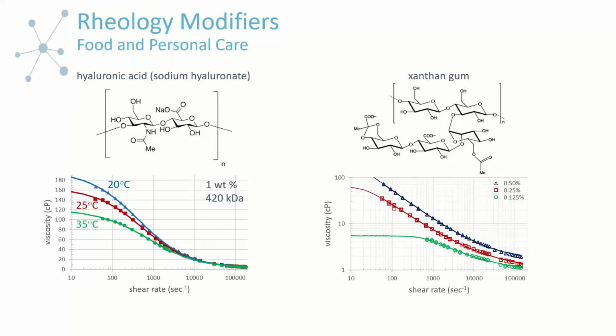Okay, so starting off then, as I said, we wanted to talk about some rheology modifiers that would feed into the food, beverage industry and some personal care products. So on the left, we have a common rheology modifier, and actually this is the case where you would have a polymer that is both controlling the rheology and also an active ingredient, particularly in skincare or cosmetics. So the sodium hyaluronate or hyaluronic acid, in addition to being a high molecular weight polymer, is also quite hygroscopic. So it retains and attracts moisture.